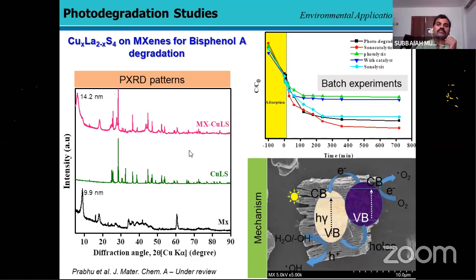Then we found good results using sonocatalytic degradation. Sonocatalytic degradation is nothing but sonication along with visible light. We have also checked photodegradation, sonocatalytic degradation, photolysis with photocatalyst, and sonolysis. Among them, sonocatalytic degradation had much higher efficiency than the other methods developed here.